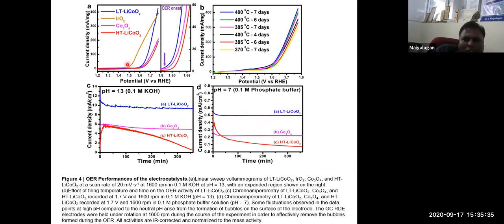So when you look at the oxygen evolution reaction, it is an upward peak. Oxygen evolution reaction is oxygen production. These are upward peaks in electrochemistry. So when this peak is higher, that means it's a better catalyst, and also the onset potential should be lower for a good catalyst. So when you look at this oxygen evolution reaction, look at the blue one, low temperature lithium cobalt oxide, and iridium oxide.